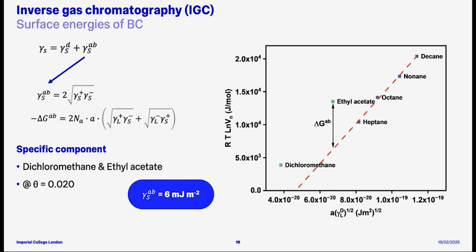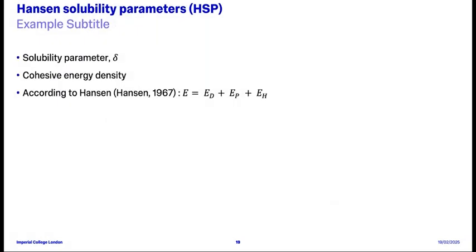But despite knowing the dispersive and the polar components of the surface energy of bacterial cellulose, it still didn't add much to our understanding of why bacterial cellulose is better dispersed in ethanol-water mixture than water alone. Further information is required to answer this question. So here we are then referring to the theory of solubility parameters. Solubility parameters have been a very useful tool in interpreting the miscibility and compatibility between materials and are widely used in the polymer and pharmaceutical industry.